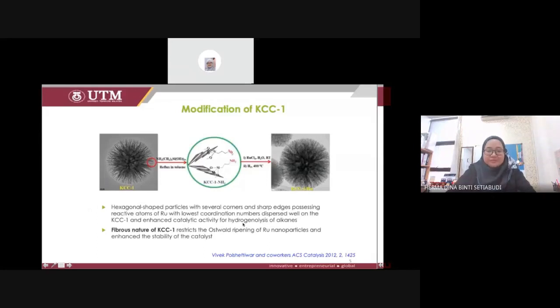They tested on the hydrogenolysis of alkanes. Okay, why could this happen? This is because the fibrous nature of KCC1 restricted the Ostwald ripening of ruthenium nanoparticles. Ostwald ripening is like a sintering, not the same but like a sintering. With the restriction, the ruthenium nanoparticles remain in smaller particles. So this smaller particle dispersion can enhance the stability of the catalyst.